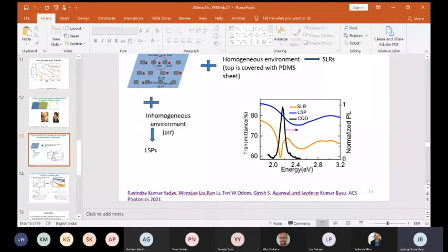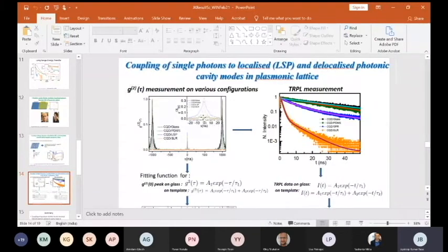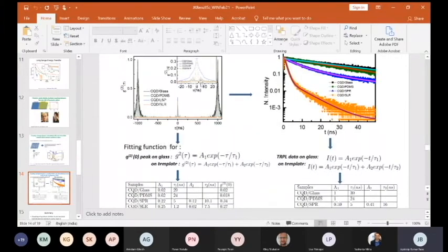But when you look at the second order autocorrelation function G2, you see a very, very clear signature. So if you have isolated quantum dots, the signature of a single photon is extremely low. If you look at this curve, I don't know whether you can see it. Unfortunately, I can't zoom out more. So if you see this flat curve here in green, basically it's almost immeasurable. So this is a very clear signature that these are single photons.